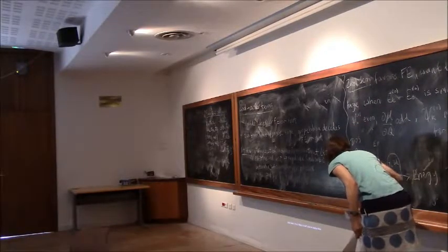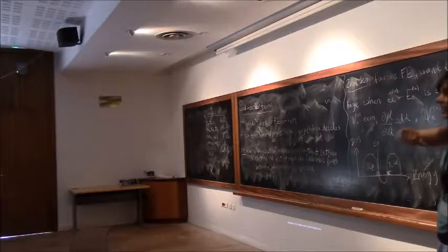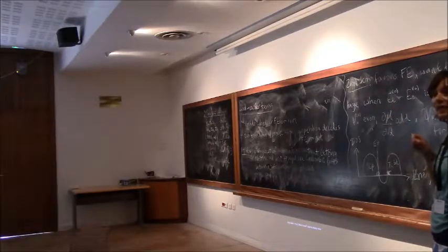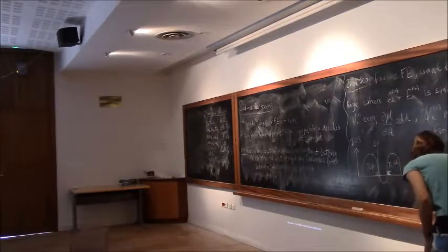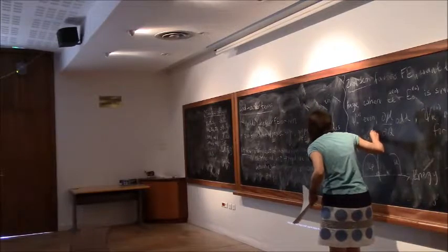And now I make my first excited state. I take an electron out of the oxygen 2p band and I put it in a titanium 3d. So now I have taken out an odd electron, if you like, and put it into an even state. My 2p orbital was odd, my 3d orbital is even. So my first excited state, psi 1, 0, is odd. So for any D0 transition metal oxide, the numerator is non-zero for the lowest excited states.